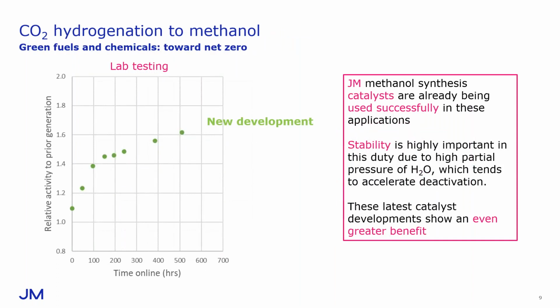Another exciting prospect for this development is in the area of green fuels and chemicals production via CO2 hydrogenation. And having a stable catalyst is potentially even more important in this duty due to the high partial pressure of water produced as a byproduct, which tends to accelerate deactivation. And we have found in our lab tests that variants of this development perform significantly better in these duties than prior generation catalysts.